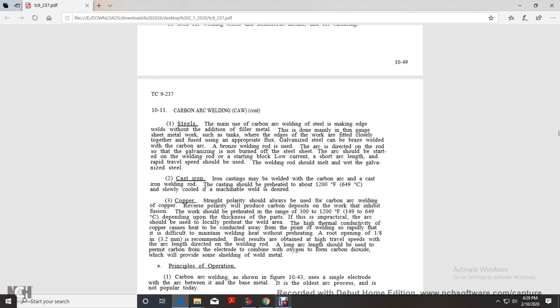Copper: straight polarity should always be used with carbon arc welding of copper. Reverse polarity produces a carbon deposit on the work that inhibits fusion. The work should be preheated in a range of 300 to 1200 degrees Fahrenheit depending upon the thickness of the part. If this is impractical, the arc should be used to locally preheat the weld area. The high thermal conductivity of copper conducts the heat away from the point of welding so rapidly